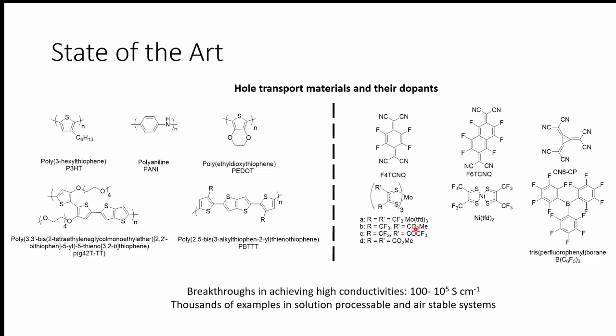So as we discussed, since we have 2 types of doping, we will have 2 types of materials. Hole transport materials are the materials that we can oxidize easily with those dopants. And these are some examples of the most commonly used polymers we have, and they have been heavily researched. There are hundreds of papers on multiple of them, and we know a lot of information about them, as well as their dopants. The conductivities we were able to achieve are between 100 all the way up to 10 to the power 5, and these are solution processed. They are air stable, so we don't have a problem innovating in that space.